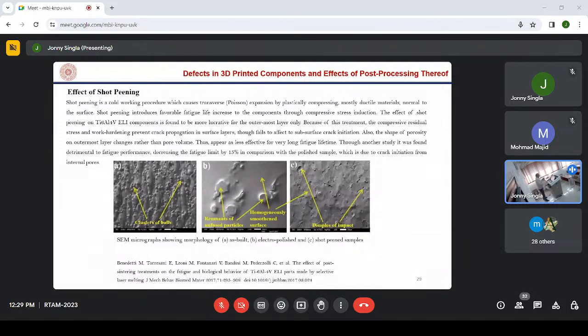Then effect of shot peening. This is another post-processing technique. Shot peening is a cold working procedure which causes transverse expansion by plastically compressing mostly ductile material normal to the surface. Shot peening introduces a favorable fatigue life increase to the component through compressive stress induction.